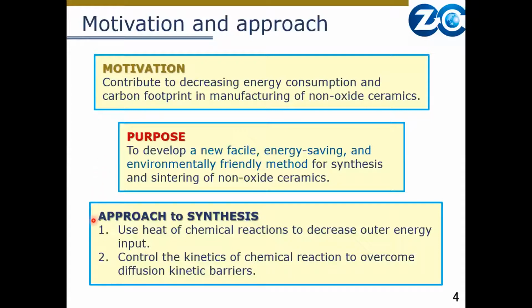And my approach to synthesis is based on two ideas. First idea is to use heat of chemical reactions to decrease outer energy input. Actually, the majority of chemical reactions used to synthesize non-oxide ceramics are exothermic. However, despite that fact, high temperatures and long hours of treatment are used. The reason is kinetics of the chemical reactions. But I consider that if we can control the kinetics of chemical reactions to overcome diffusion kinetic barriers, we can decrease temperature and time necessary for synthesis.